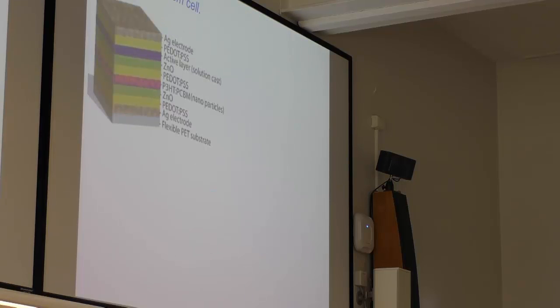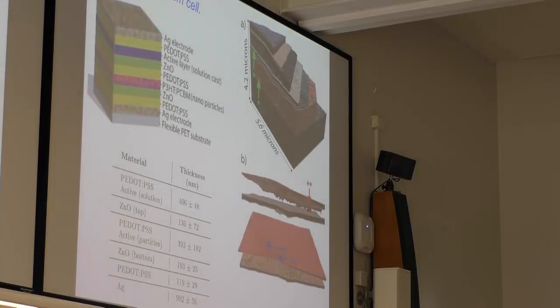Here's another example with a related technique, which should be of relevance to this audience, where we are looking at a stack of organic materials, PEDOT:PSS, zinc oxide, etc. It's a tandem cell, meaning that there are two photoactive layers here to increase the performance. But our motivation for looking at this is to see whether we are able to resolve the various layers. And indeed we are, and this study could also be correlated with the performance of these cells, to point out that short circuits like the one that we have resolved here are of course reducing the performance of the solar cell.